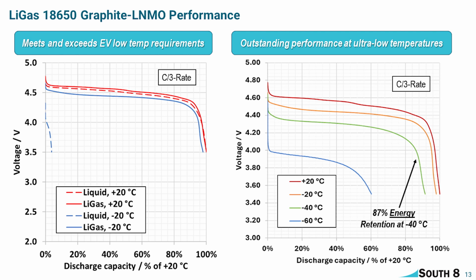So the two red curves are showing these graphite LNMO cells. The solid curve with our LiGas electrolyte, the dashed curve with your conventional liquid-based electrolyte. At room temperature, they're showing pretty similar voltages, nominal voltage right around 4.6 volts or so, and both tracing right on top of each other.